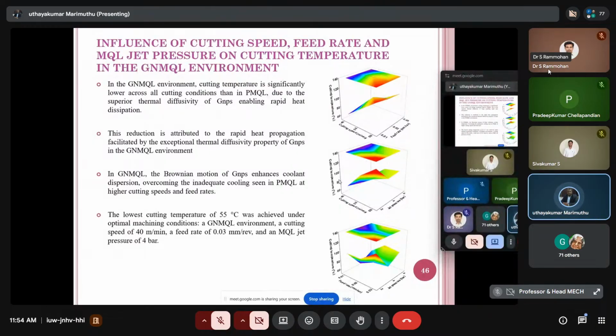So cutting temperature is significantly lower across all cutting conditions when you compare it with PMQL, due to the superior thermal diffusivity of GNPs. That is the important point here, enabling rapid heat dissipation. So heat dissipation is more when compared to the other mechanism. This reduction is attributed to the rapid heat propagation facilitated by the exceptional thermal diffusivity property of GNPs in the GNMQL environment. The Brownian motion of GNPs enhances coolant dispersion, overcoming the inadequate cooling seen in PMQL at high speed. So PMQL at high cutting speeds and feed rates is inadequate. That is the inference we are going to submit after this experimentation.